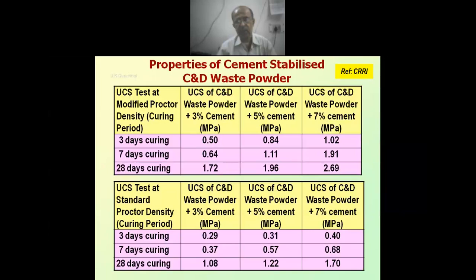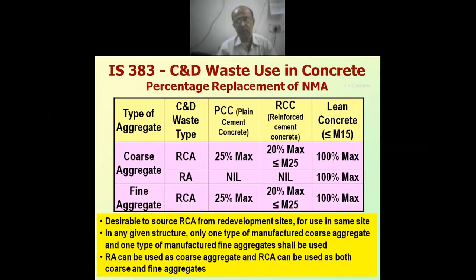Okay, let's see the Proctor test and what the strength values are. Unconfined compressive strength values. So we require around, this is 1.9 MPa. So we require around 6% cement for the subbase layer, and for base course, of course, it's not very high. This is when we use C&D waste powder. If we add the C&D waste aggregate also, these values will get higher. This is totally for the powder type of material.